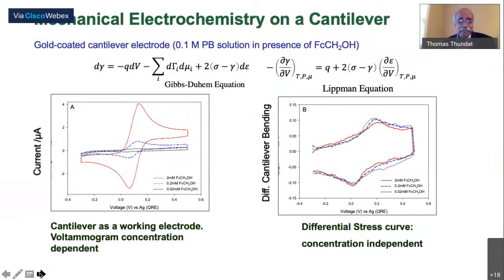And you can also do electrochemistry if you want. This is the current versus voltage, with respect to a silver reference electrode, or actually quasi reference electrode. So you can see that this is the Gibbs-Duhem equation. You can actually ignore some of these parts. Basically, you don't need the full Gibbs-Duhem equation. Basically, it's showing the current versus voltage. This is a cantilever as the electrode, and for different concentrations, you can see this is a ferrocene methanol reduction oxidation peak, and you can also measure the bending at the same time, and the bending doesn't change with the concentration. It looks the same. And it gives you some more information that all the interactions are happening at the very interface. That's why the bending doesn't change with concentration.